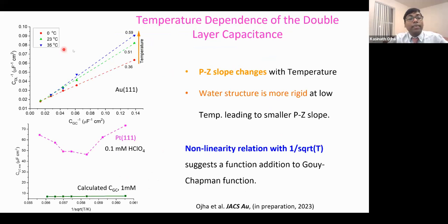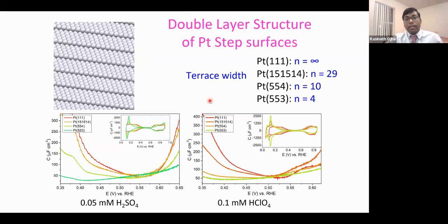And we also look at the Parsons-Zobel slope at different temperatures, and as we increase the temperature, our slope is increasing. That means the slope increasing indicates that we have a smaller experimental capacitance value than the calculated one. Why does it become a smaller capacitance value? At high temperature, those interactions of ions with the surface are disturbed, so no more ion accumulation is happening, so the slope is increasing. I think I'll skip this system now because it's already too much time.